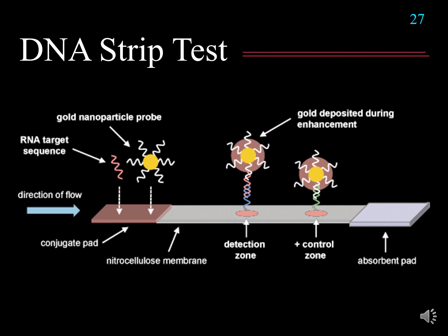And again, because gold nanoparticles are red, it may not be deep enough to see by the naked eye. We can also enhance the color by adding silver ion into our system. So the silver ion will be reduced on top of the gold and change the color to deep black. So we can improve naked eye detection using silver ion as well.